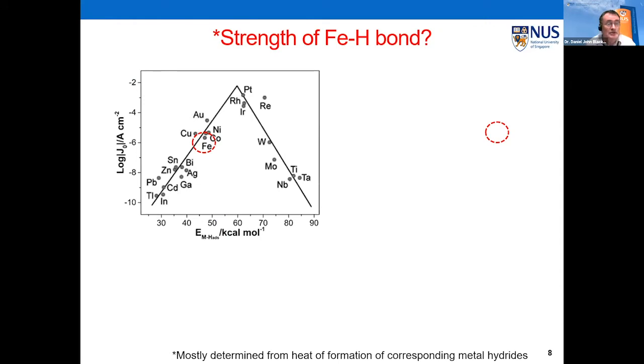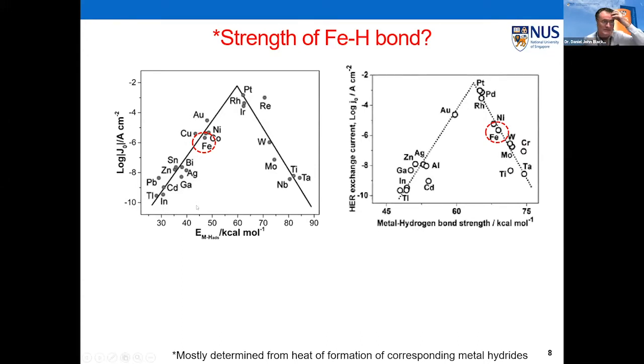And that comes down to the strength of the iron-hydrogen bond, and even here we're not very good. If you Google the volcano plots, which were done by Trasatti all those years ago, there are actually 2 types where you'll find the iron. I tried to find how they were measured differently. Most seem to be based on heats of formation of the corresponding metal hydrides, but the older ones have iron on the left-hand side. That means you'd expect it to be the adsorption step. But I have some colleagues who do modeling with DFT, and all theirs have it on the other side. That means it's probably the 3rd step, and so removing hydrogen could potentially accelerate the corrosion.